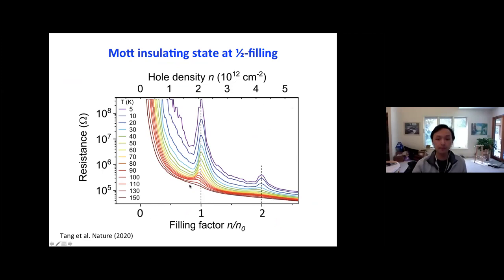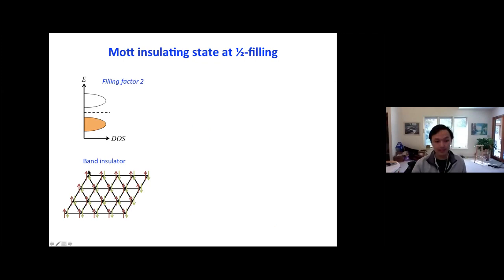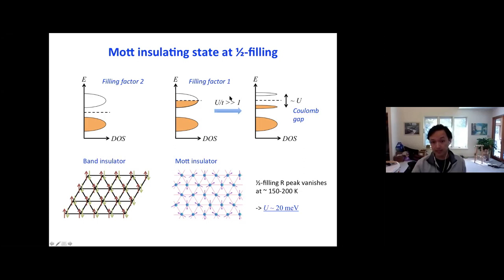Okay, and filling factor 2 corresponds to two electrons per moiré site, right? And that corresponds to a completely filled moiré band. So it's just a simple band insulator, and so we do have a resistance peak there. And filling factor equal to one corresponds to a half-filled moiré band. Without interaction, you would expect that it's a metal. But with interaction, the electrons try to avoid double occupancy of each moiré site. And you can think of it that the energy band is now separated into the lower Hubbard band and the upper Hubbard band by an energy scale roughly equal to U.